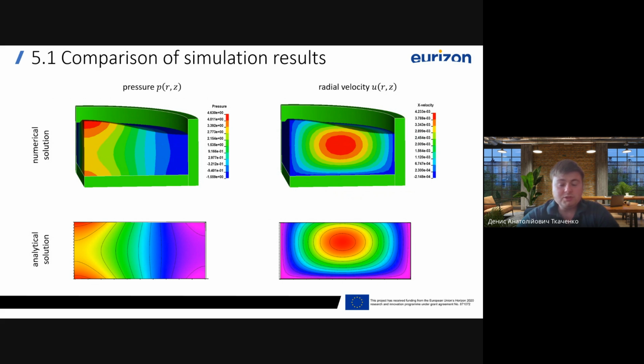Both approaches capture the same overall flow pattern: radial velocity peaks near the center and close to the surface, while vertical velocities are concentrated at the center and edge of the free surface. Pressure profiles show similar distributions with minimal decay into depth.